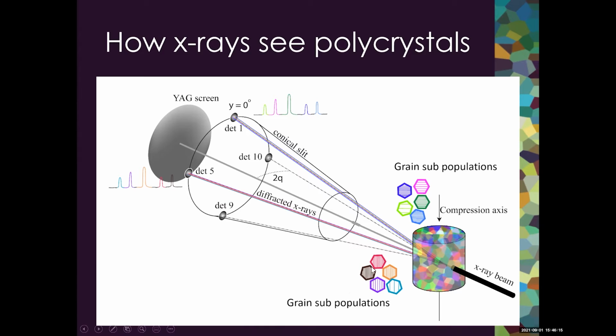Similar is the case for the transverse direction. We get a diffraction pattern with multiple peaks where each individual peak is correlated with a specific group of grains. And so each diffraction peak comes from a different grain population, which is sampling a different aspect of what is going on inside the polycrystal.